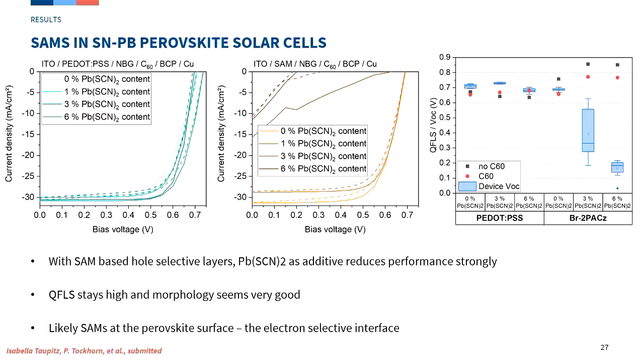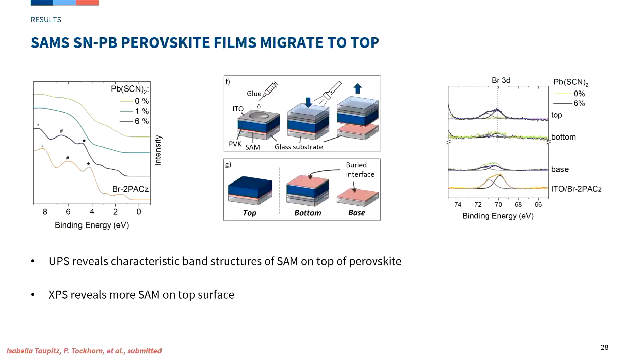However, if you then measure a solar cell, you get JV curves like that—this is what you don't want to have. It's a very bad solar cell. So everything looks very good, it has to be very good, but the solar cell in the end is very bad. So we dived a bit deeper and used photoelectron spectroscopy again to understand why, in principle, the film looks so good, the PL is very high, but the solar cell is very bad.